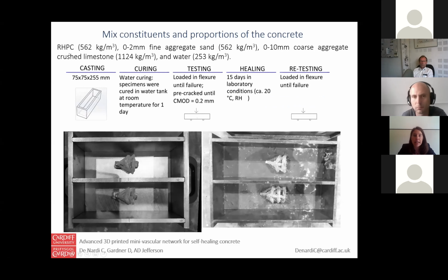So at the beginning, just to prove the concept, we used a rapid hardening cement in a ratio of 1:1:2 to 0.45. We cast prismatic samples. We demolded after 6 hours, and then we placed all the samples in the tank. We tested the day after in flexure until failure or until the crack opening was equal to 0.2 millimeters. We waited 2 weeks for the healing process, and then we retested all the samples until failure.